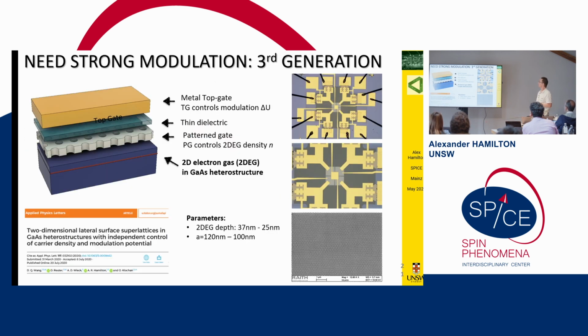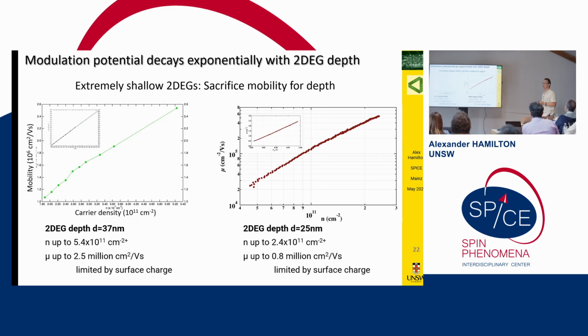And then our third generation of devices started working about 2 years ago. Now we can really make large lattices, multiple gate layers, and finally we can get very high mobility. And one of the tricks was you have to get the two-dimensional electron system very close to the surface, but keep a high mobility. So these 2D electron systems are 25 or 30 nanometers below the surface, but still have very high mobility.